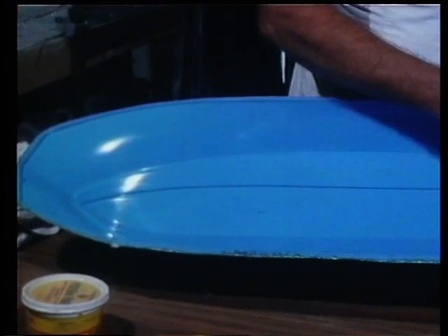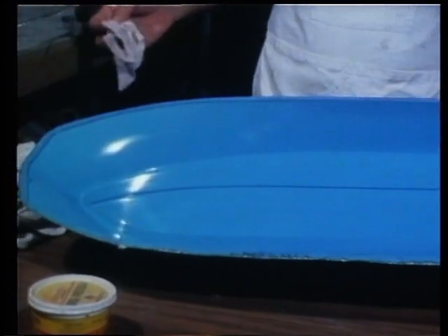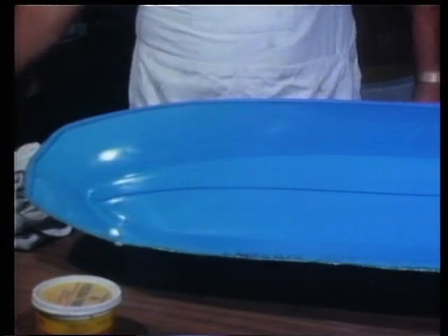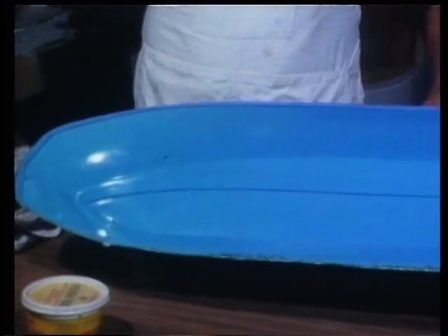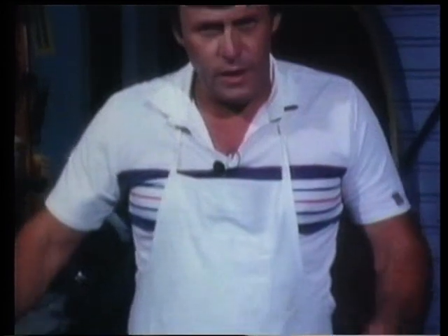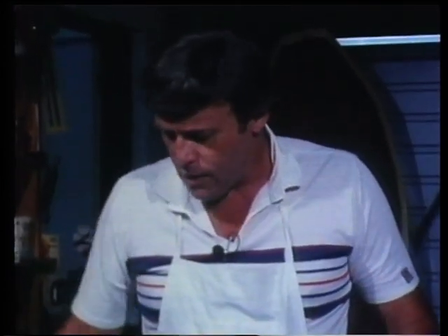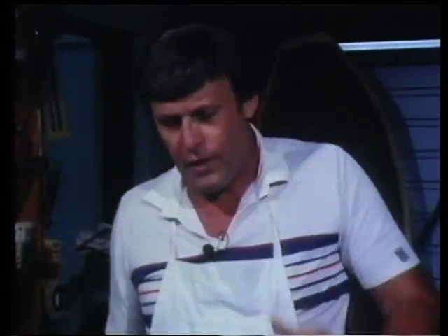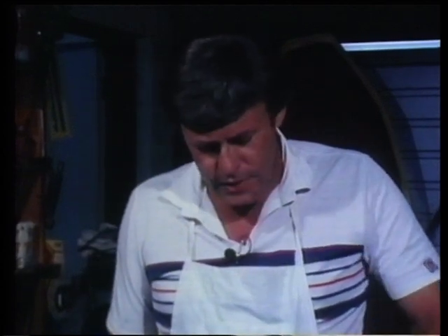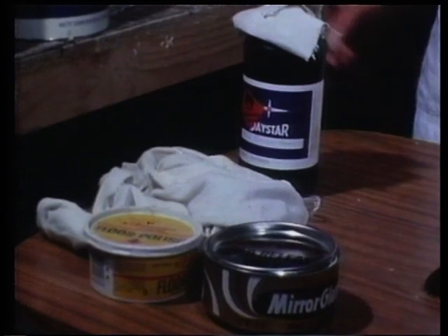Now that's pretty well ready for the next step, which is the application of the gel coat. But you must make absolutely certain that that PVA is completely dry before you apply the gel coat. Now it's alcohol based, so the alcohol flashes off quite rapidly. It takes 10, maybe 15 minutes to dry, so we'll come back as soon as that happens.